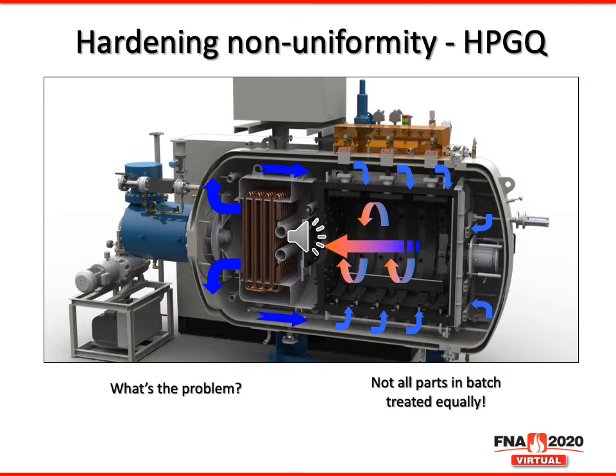Now, most designs have features that improve the flow path to ensure that each part is receiving gas that is both low temperature and high velocity to maintain the overall heat transfer ability of the furnace itself. How? Well, let's take for instance the fact that the blower can be up to 600 horsepower in this case. Or that we can use pressures up to 25 bar of different gases like nitrogen or even helium. This allows for more gas to be closer to the surface of the parts, allowing for more heat transfer from the parts to the gas.